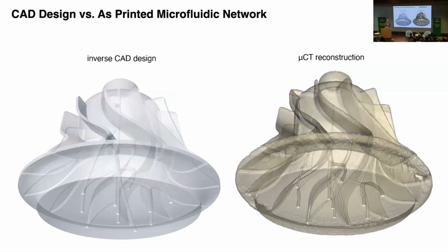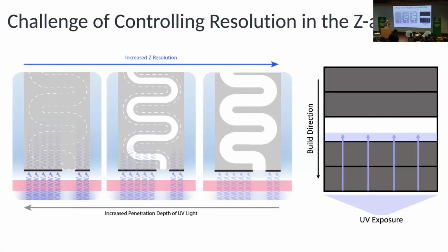But the most interesting thing that we didn't anticipate is, son of a gun, the channels are open. Why is that? Because if we just had normal CLIP, light would cure that. The resin's oxygenated. And we can have a turnover rate that keeps it clear. So we've now eliminated one of the key problems with 3D printing microfluidics. And so look at this.